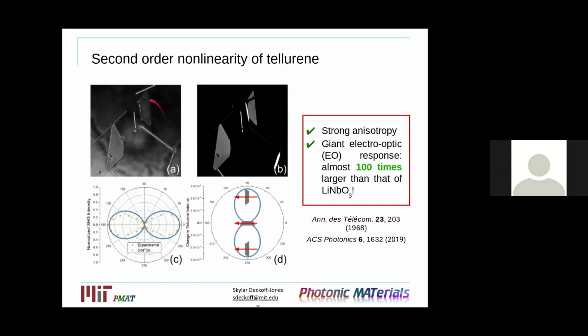So this is actually second harmonic generation measurements of the tellurene. On the left, we have an image of the reflected fundamental as it's scanned across our tellurene flakes. And so we see all the various trapezoids and some long spindles of the tellurene, all with similar intensity. However, when we collect just the second harmonic generation, we get a very strong second harmonic generation signal, which is quite stronger than the other 2D materials we measured, and even 100 times larger than lithium niobate.